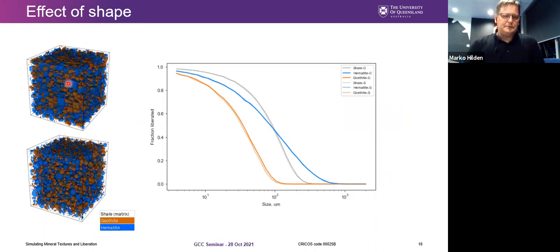As I mentioned before, the model can simulate cubes or spheres. And actually, the effect of the shape turns out to be not very much at all. So you basically get very similar liberation distributions from these shapes. I tend to suspect that the effect of shape, especially when you have a wide particle size range, is sort of overrated, really.